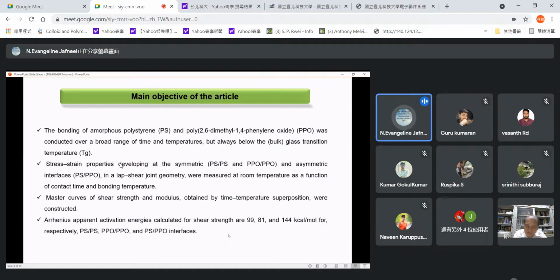The main objective of the article is that the bonding of amorphous polystyrene and PPO was conducted over a broad range of time and temperature, but below the glass transition temperature. The stress-strain properties developed at the symmetric and asymmetric interfaces were measured at room temperature as a function of contact time and bonding temperature. Master curves of shear strength and modulus were constructed, and the Arrhenius apparent activation energies were calculated for shear strength.